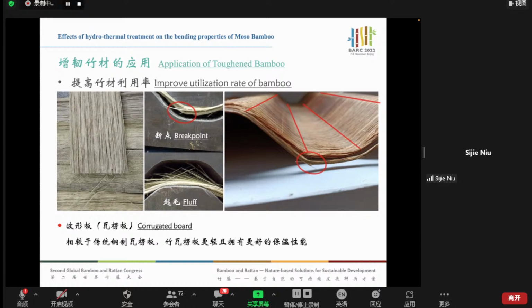Originally, we can use steel plus foams to increase the insulation and keep the heat. We can use a bamboo, actually corrugated boards instead of foams. However, the bamboo boards are very easy to break. You can see even before the lamination process, the board or the mechanical features already lost before adding pressures.